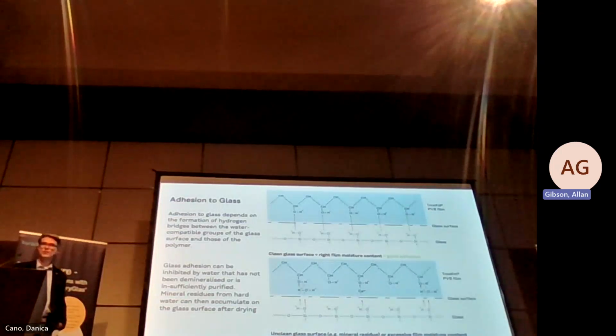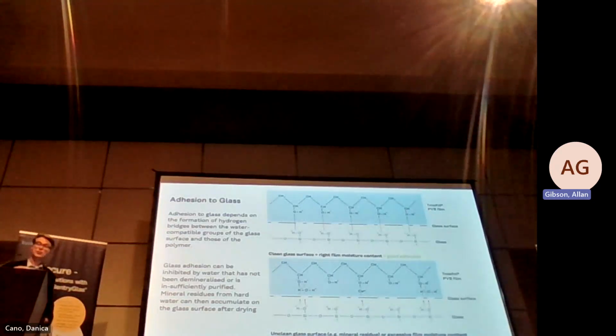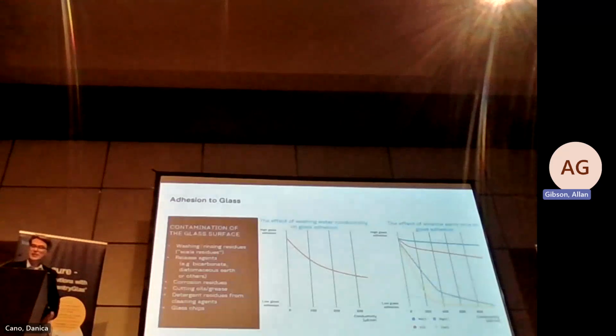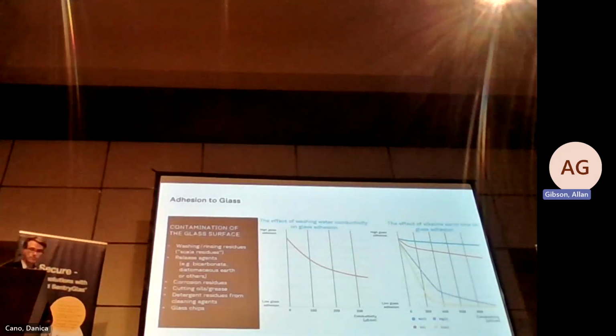So now let's look at some of those causes of delamination. As a manufacturer, we run extensive tests to ensure the suitability and the production quality of the material. From a quality perspective, ISO 12543 Part 4 provides test methods for durability, and it mimics the excessive conditions expected when the material is in an installed state. The three main objectives are to look at the aesthetics and measure bubbles, cloudiness, and ultimate delamination. This is a similar methodology used for sealing compatibility, which I'll go through later.